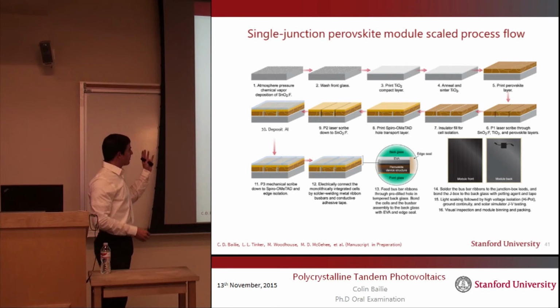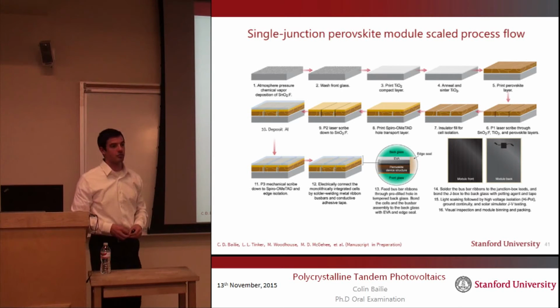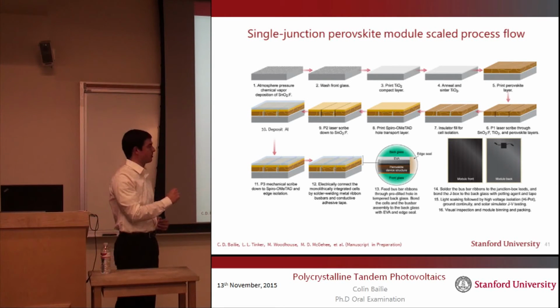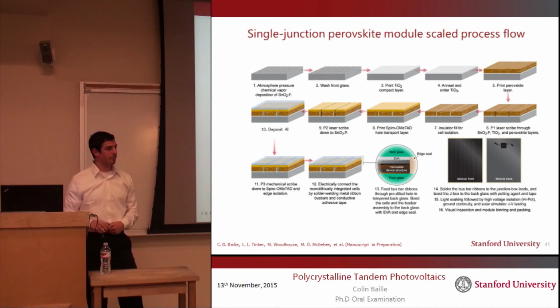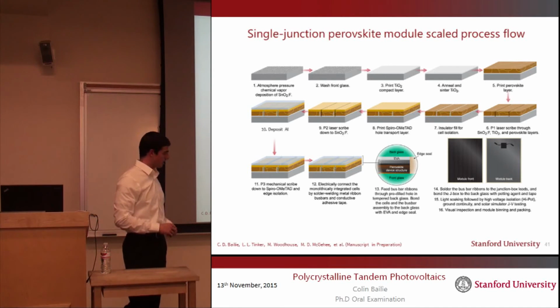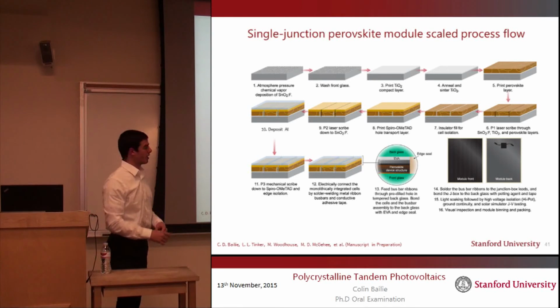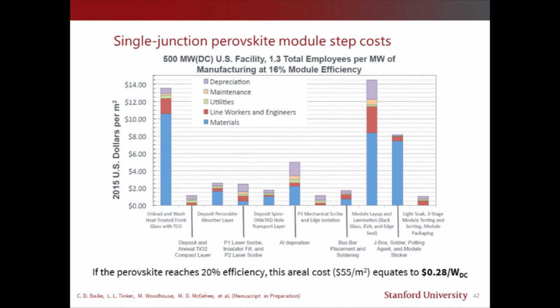This is a process flow for a single junction perovskite module where all the active layers are solution processed in an NIP style architecture, and the cell interconnections are defined as in a standard thin film cadmium telluride-like architecture. And then, when we add up all of the step costs, we can arrive at a total areal cost for the single junction perovskite module of $55 per meter squared, which if the perovskite were able to reach 20% efficiency in a single junction module, would equate to 28 cents per watt. In this chart, I'd like to point out that all of the small columns in the middle have to do with depositing the perovskite and surrounding layers, as well as defining the interconnections between these cells,